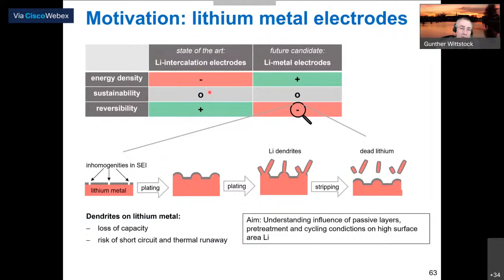So now we had a new project where lithium electrodes were again in the focus. And this is a survey which shows you the advantages and disadvantages of lithium metal electrodes. High energy density, but low reversibility. And this is due to the tendency to form high surface area lithium, like lithium dendrites, and also then the stripping. So we would like to understand that and maybe devise additives or procedures which mitigate that effect.